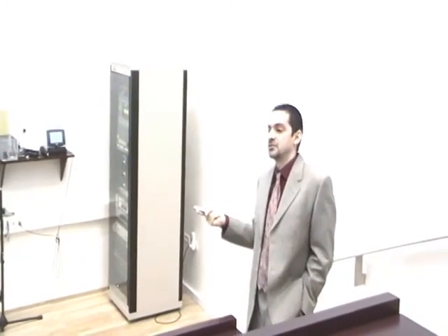This model is a nearest neighbor model, since the sums inside the brackets are sums over the nearest neighbor atoms. D and R are the bulk, so basically D is the distance of the pure material, and R is actually the distance of the atoms in the quantum dot. So basically, R will be the quantity we are going to calculate in this kind of model. Theta is the unrelaxed tetrahedral bond angle, and alpha and beta are empirical material-dependent elastic parameters.